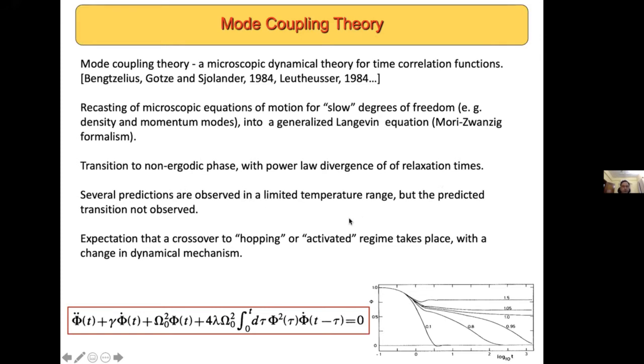However, where such a divergence of relaxation times is predicted, in practice, one does not see it. One sees a window of temperatures over which the dynamics is obeying the predictions of mode coupling theory in several ways. But as you get close to the divergence temperature, you begin to have increasing deviations, and the relaxation times remain finite. But what one understands is that the mode coupling theory captures some aspects of structural relaxation slowdown as one goes to low temperatures.